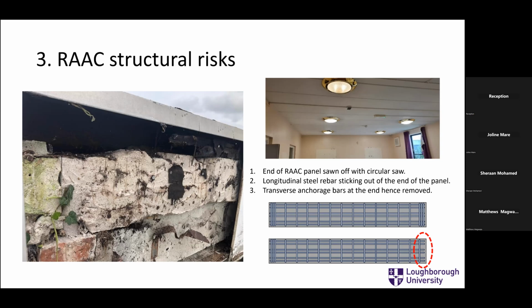But the big problem, and this is where the main risk is, in some instances, they've not just reduced the length of the longitudinal steel, the anchorage transverse steel at the end that anchors those bars and stops them slipping all the way through, they've sawn off. So imagine the anchorage of those longitudinal bars, which take the bending moment, because the AAC is so weak, there's very little anchorage, very little at all. So they need these welded transverse bars at the end to anchor at the ends. Otherwise they slip through. And if you saw them off, you've got some bars there that can slip through when you increase the load. So this is the key concern. And this is the critical risk that we've seen in many different types of buildings. A small proportion, but critical. So it's not the fault of the RAAC as a material.